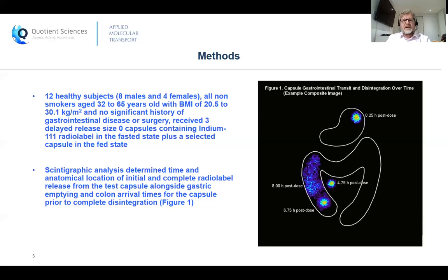for an individual study subject and comprises an overlay of selected scintigraphy data collected at 0.25, 4.75, 6.75, and 8 hours post-dose. The white outlines of the stomach and colon for this subject were generated within the scintigraphy analysis software based on a 99m technetium radio-labeled drink taken by each subject alongside dosing of the indium radio-labeled test capsule. The colored pixels visible represent the actual amount of radiation reaching the gamma camera face, and you can see that the capsule with its radio-labeled contents remain intact through the 0.25 hour time point where it's in the stomach, and at 4.75 hours where it's actually in the small intestine, which isn't outlined in this composite.